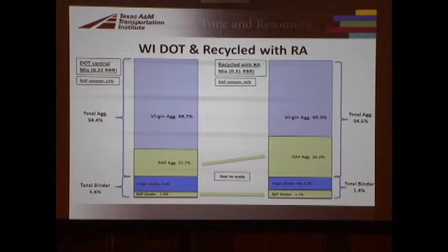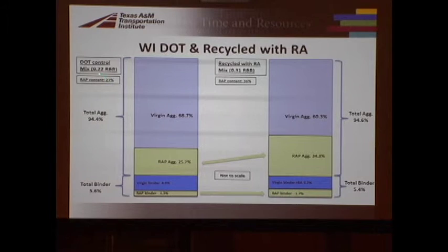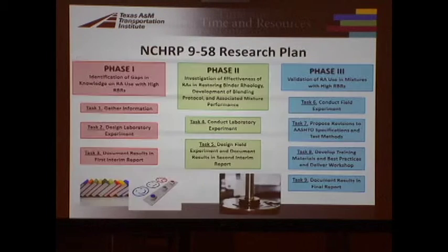Currently in Wisconsin, they're allowing a 0.22 RBR with all RAP. They put down a mix with this, what we call the DOT control mix. And then we're trying to see, can we go up to 0.31 RBR by using a recycling agent? When we do that, our RAP aggregate goes from 26 to 34%, and our virgin binder goes down from 4.3 to 3.7%. So the idea is, can we get the benefits that we want by using recycling agents to mitigate the effects of stiffening and embrittlement? And do those recycling agent effects last with aging? That's a big thing. Maybe they work initially, but do they last with aging?